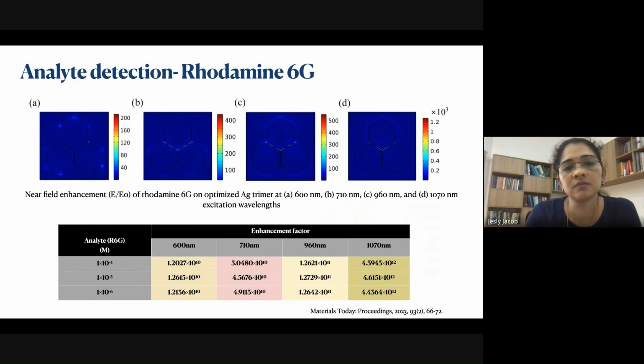It's a very good analyte. And so the near field enhancement of rhodamine on optimized silver trimer is taken for 600 nanometer, 710 nanometer, 960, 1070 nanometer excitation wavelengths. And we have just shown the enhancement factor here and changed the analyte concentration here. You can see that even a small analyte concentration is giving a very good enhancement factor. So it is also evident from this that it can be detected from many other dyes. That is, even if there are many other dyes in it, it can detect rhodamine 6G particularly.